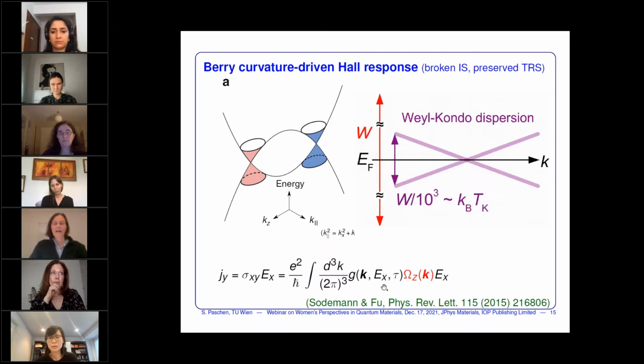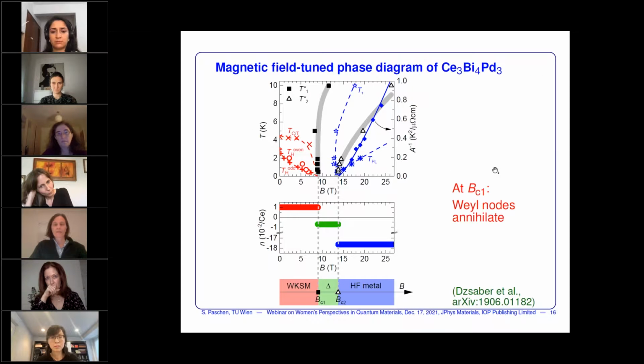So why we detected it, and the way we understand it, is that it is due to the extreme mass renormalization we have in these strongly interacting systems, and the fact that in these systems the Weyl node is quite precisely tuned to the Fermi energy, so that we can have this very large effect. The second aspect of this strong correlation in this topological system is that the system becomes very tunable. So we needed only a relatively modest field of 9 Tesla to suppress this Weyl physics altogether. And from the properties we observed, we have to conclude that what we actually do here is to annihilate these Weyl nodes, which is something quite exciting.